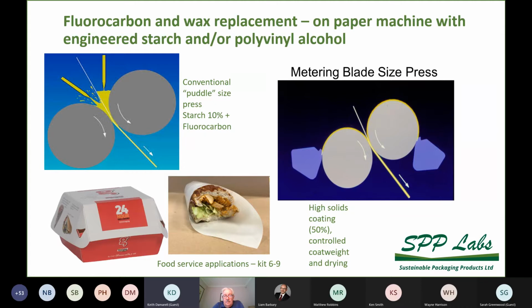These are used today in paper making quite routinely to apply things like starches and synthetic waxes to achieve a level of water resistance to paper, so it doesn't all act like toilet paper essentially. And this is where often things like fluorocarbons are added today. These on-machine coating systems are now being utilized to apply what is effectively water-based and often natural-based materials like engineered starches, sometimes some latices and other vegetable oil technologies, and even to some extent polyvinyl alcohol, water-soluble materials, to achieve grease resistance and in some cases some levels of moisture resistance. So on machine today, you can produce alternatives to wax treatment and alternatives to fluorocarbon treatment.